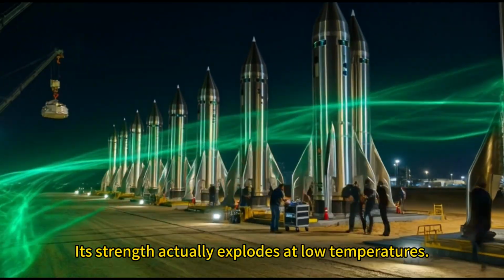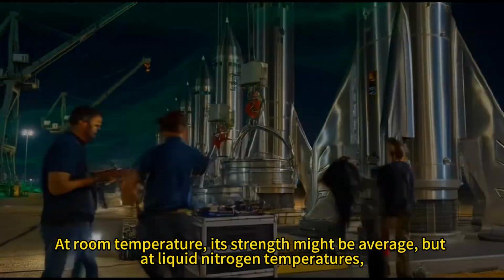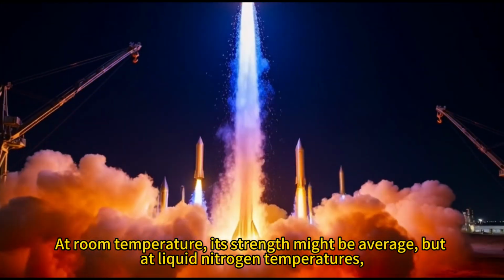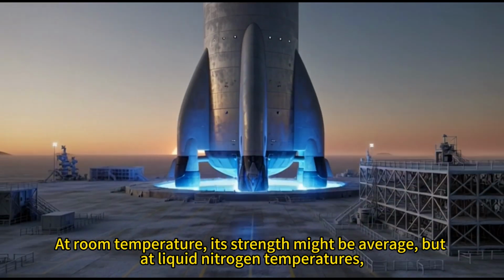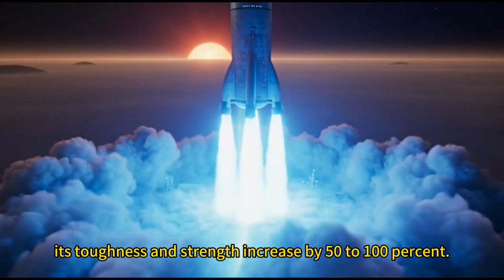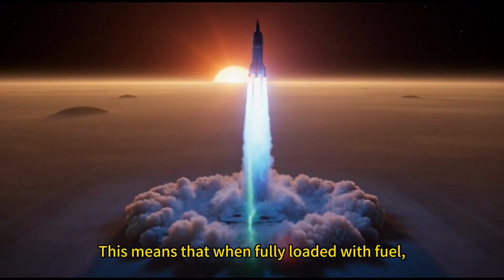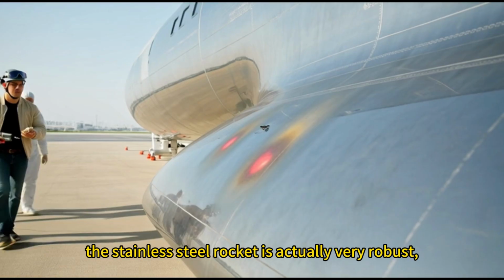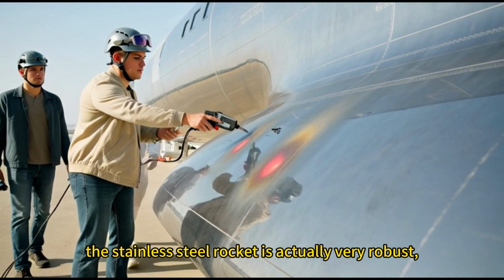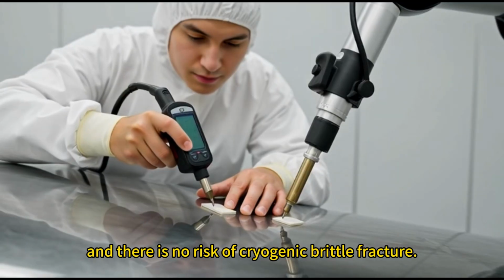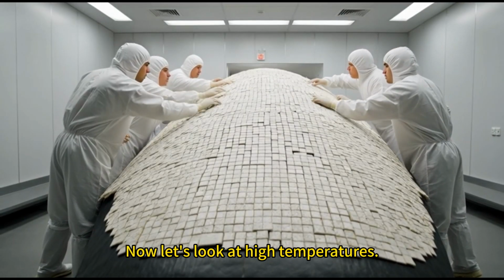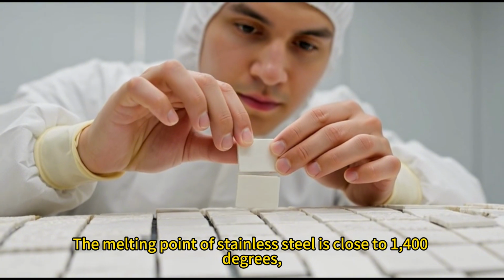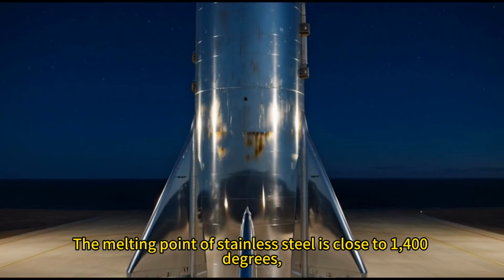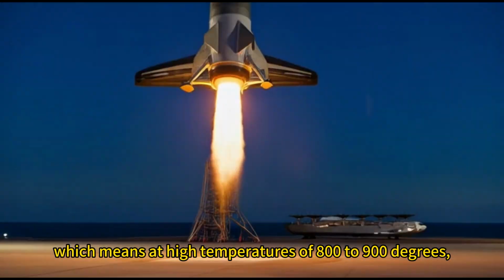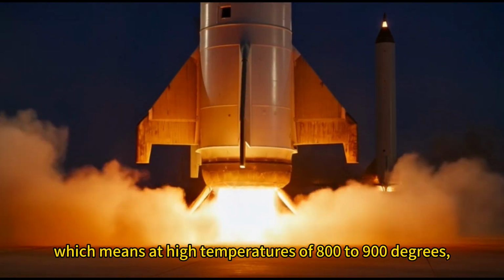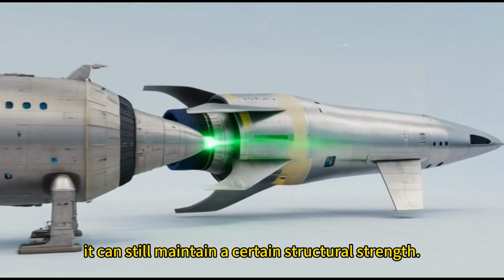Its strength actually explodes at low temperatures. At room temperature, its strength might be average, but at liquid nitrogen temperatures, its toughness and strength increased by 50 to 100%. This means that when fully loaded with fuel, the stainless steel rocket is actually very robust, and there is no risk of cryogenic brittle fractures. Now let's look at high temperatures. The melting point of stainless steel is close to 1,400 degrees, which means at high temperatures of 800 to 900 degrees, it can still maintain a certain structural strength.